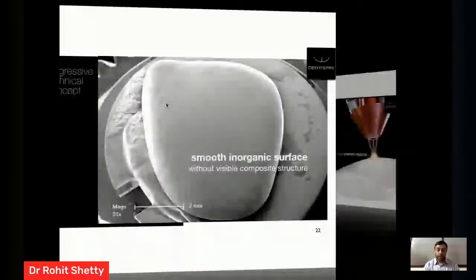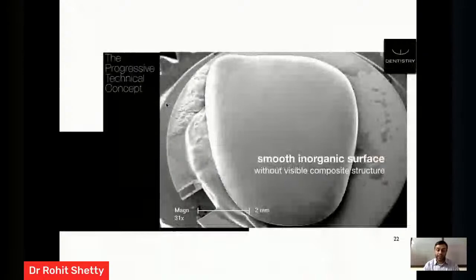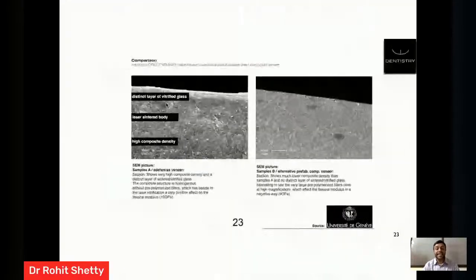The composite core is both strong and flexible with a coating laser, and what we end up with is a smooth inorganic surface which has been devoid of any resins that has been extracted by the laser beam. The SEM photograph basically shows us three distinct layers: an upper distinct layer of vitrified glass, which is responsible for the glossiness, the translucency, and the lifelike appearance of these veneers; a laser sintered body, which is completely homogeneous, devoid of resins, and this is responsible for the higher flexure modulus, which I mentioned earlier, enables the veneers to be well adapted onto the convex surfaces without breaking.